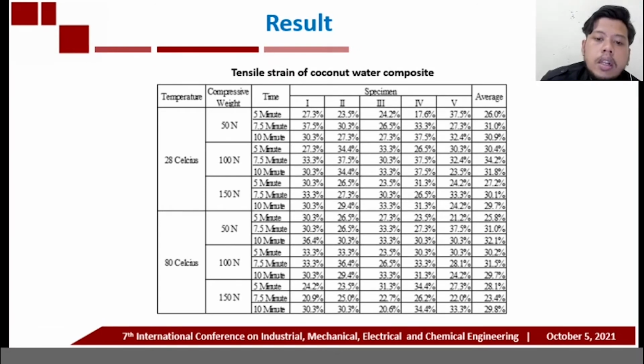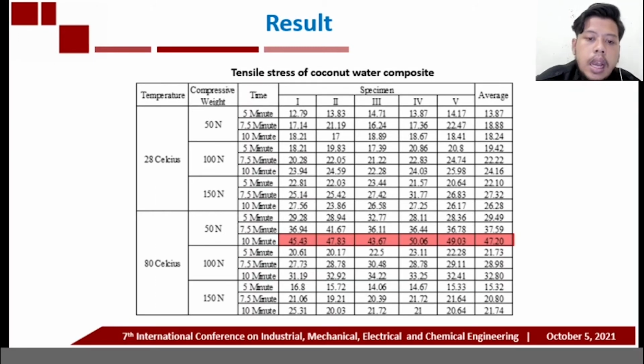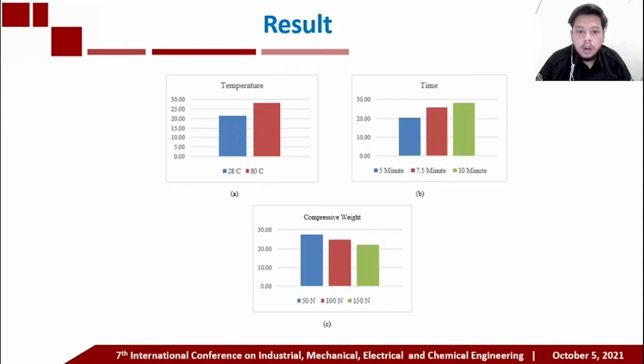And this is the result of tensile strain of coconut water composite. From the table, the highest strain specimen is with temperature treatment 28 Celsius, compressive weight 100 Newton and compressive time 7.5 minutes, obtaining strain value 34.2%. And this is the tensile stress of coconut water composite. From the table, the highest stress value from the coconut water composite is with temperature treatment 80 Celsius, compressive weight 50 Newton and time 10 minutes, with average value 47.20 megapascal.